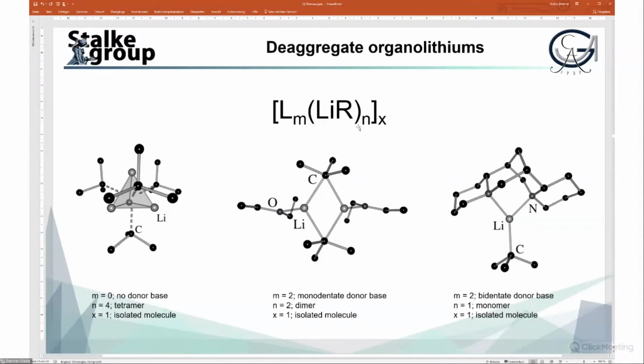If N is 4, then we have a tetrahedron, like here, the tertiary butyl lithium structure, with capped triangles in the tetrahedron, no donor base, no ligands attached. That would mean we have an isolated molecule, not a coordination polymer as in methyl lithium.